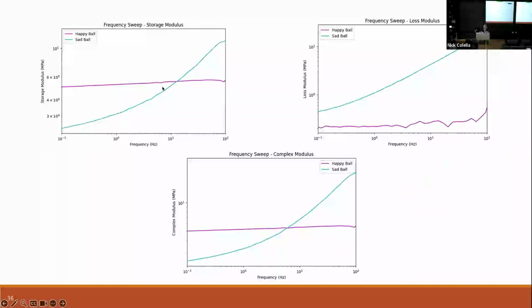So this is comparing the storage moduli. We can compare the loss moduli on its own. We can compare our loss moduli up here in the top right, and we see a much higher loss modulus all across different frequencies for the sad ball. And then we see a change in the storage modulus as a function of frequency for the sad ball, while the happy ball has a consistent response. So what that means is, if you push quickly or slowly on the happy ball, it's always going to feel about the same. If you push quickly or slowly on the sad ball, it's going to feel much different. So we get much higher resistance if we squeeze quickly on the sad ball, and much lower resistance if we squeeze more slowly. So you can keep passing these around in case anybody wants to try any of these things that I'm talking about.